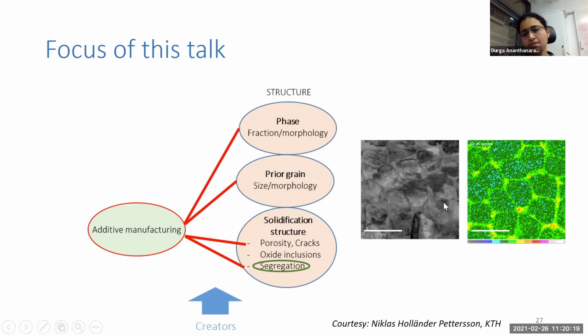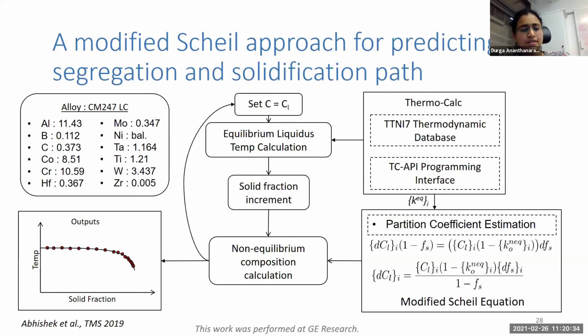So as I said, in this cell structure, we see that composition segregation happens, microsegregation. So we want to be able to predict what is the level of segregation in this scale. So for this, I give an example from this work that was performed when I was at GE Research, along with intern at that time, Abhishek. So we had a bunch of EPMA data for high gamma prime strength nickel-based superalloys. And we started with Scheil, as we do normally, and found that we are not really able to use Scheil for predicting the solidification path and segregation.